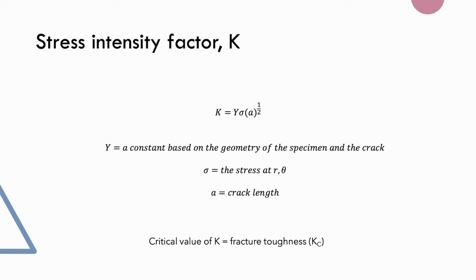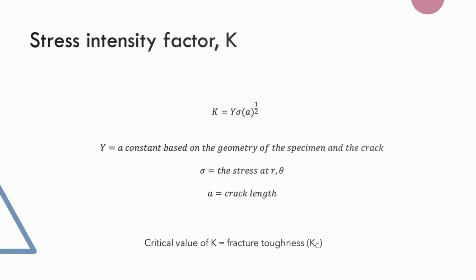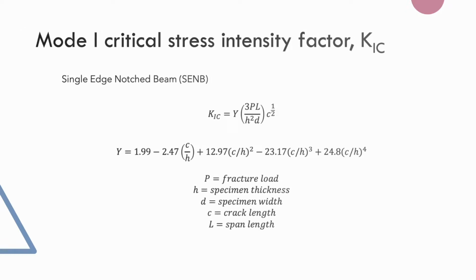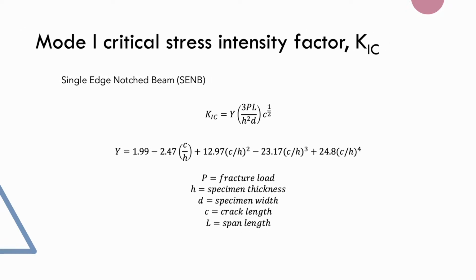Particularly, in the single-edge notched beam, the evaluation of mode I critical stress intensity factor, KIC, is based on the following classical expression. In this expression, Y is equal to the following equation: P is fracture load, H is the specimen thickness, D is the specimen width, C is the crack length, and L is the span length.